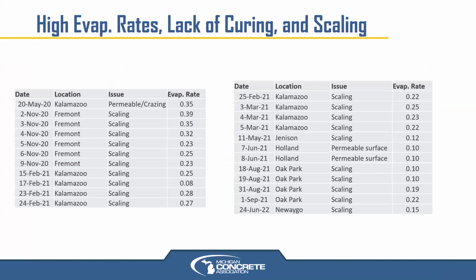So based on my experience, we've always had an issue with high evaporation rates and lack of curing, and it's typically causing scaling. I've looked at these. These are ones that I personally have been invited out to look at, from 2020 to 2022. And guess what? Those were all with Type 1 cement, before Type 1L was implemented. So to those who want to blame scaling on Type 1L, I say it's a factor, but we have always had scaling issues at times in our industry.